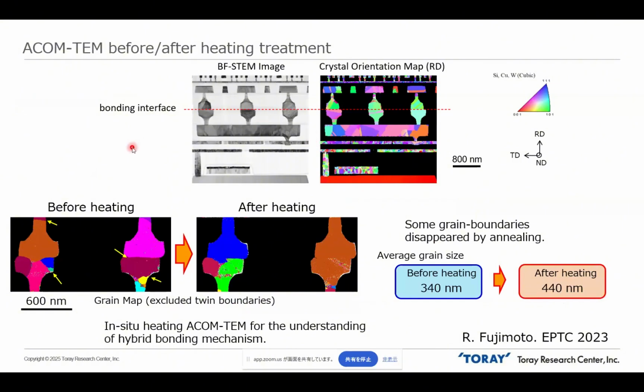Then we also use this technique on the copper-copper hybrid bonding samples. Before heating, we can see the crystal grain boundary, as shown by the yellow arrow. Then some of them disappear after heating. Then we can also calculate grain size. Before heating, the grain size was 340 nanometers, but after heating, the grain size becomes larger, 440 nanometers.